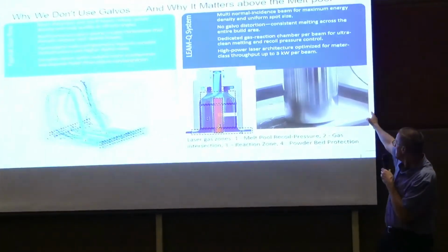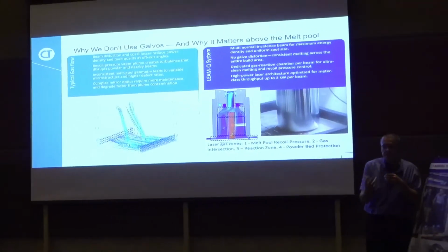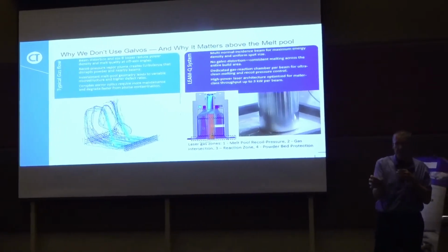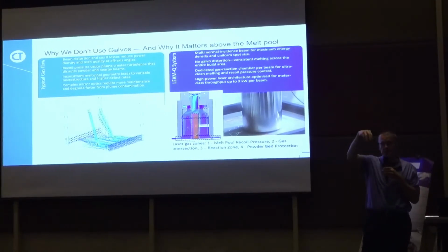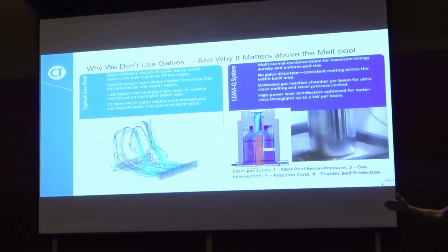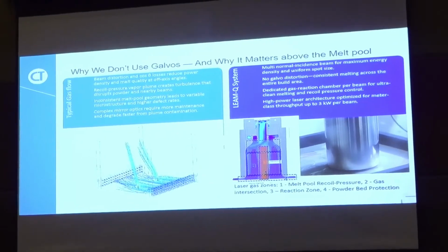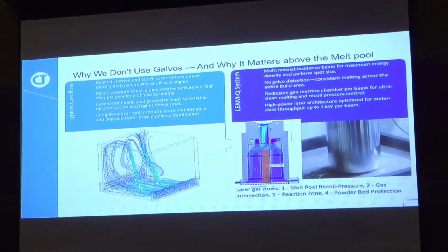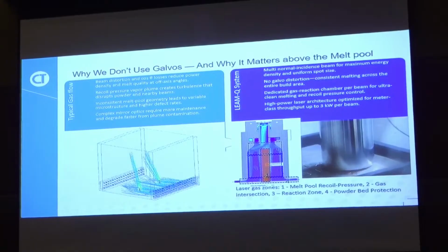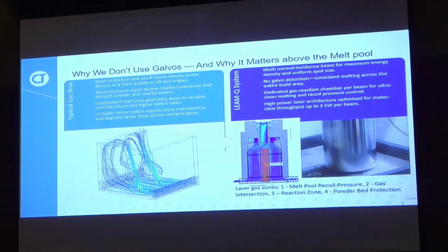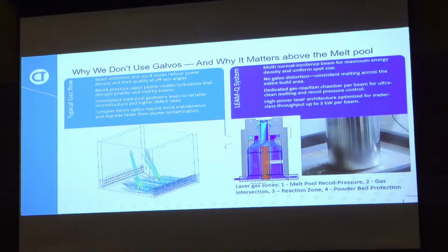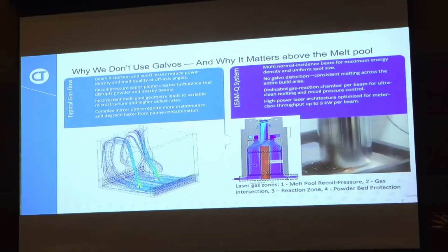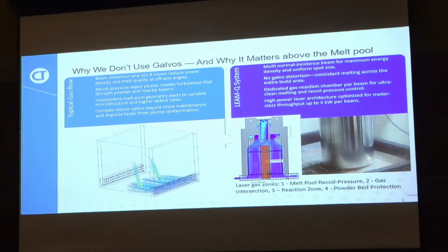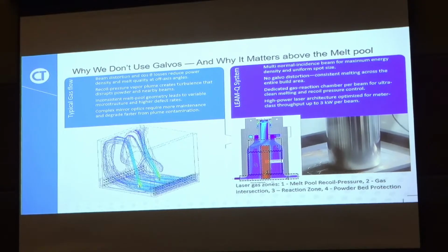And then the fourth zone is that it goes out, there's a gap in there and it goes out. So there's still gas on the outside, but every beam has its own protected area and the gas is coaxial. So it doesn't flow across, it's going coaxial with the beam down onto the surface. And it's to protect the optics, to stop the recoil pressure, to react this, and then to cool it down and to get it out.